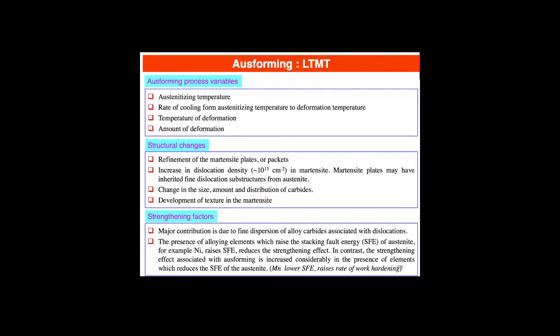our toughness, right? And that's sort of wrapping up all this heat treatment stuff into one coherent statement, right? That's our goal, right? Fine dispersion of carbides, small grains, right? And then tempering to the amount that we're going to diffuse carbon out, right? And either change our structure from tetragonal back to cubic, depending on our use case.